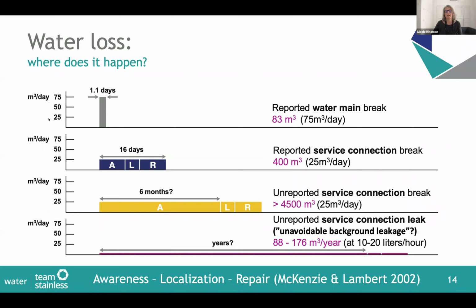So if you have a main leak, a reported water main break, that may have a leakage rate of 75 cubic meters a day. Generally you become aware of it quickly, it's reported, and you fix it within a day. So the water lost from a water main break is relatively small at 83 cubic meters here in this example. Now they suggest that maybe a reported service connection break could have a much smaller water loss of maybe 25 cubic meters per day.